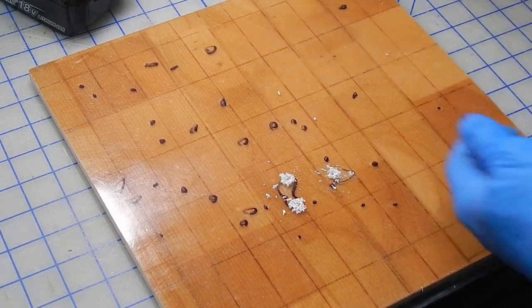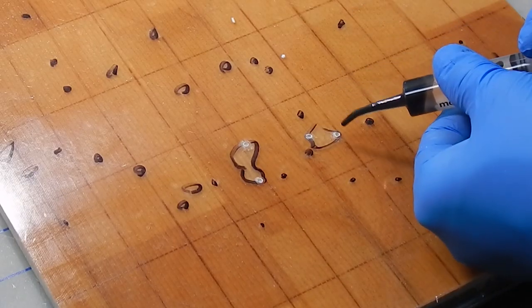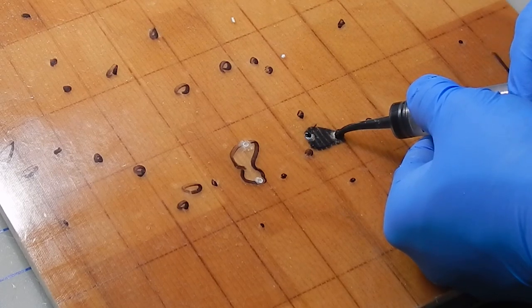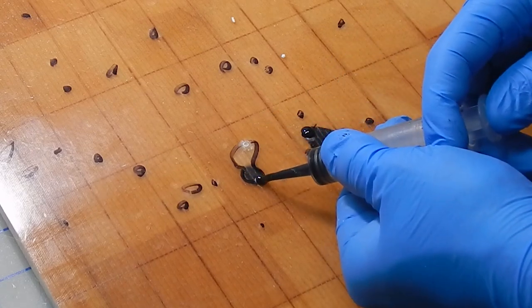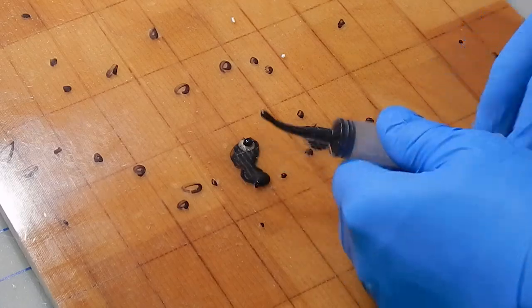So here I am drilling the holes again. And in this case there are no cells of honeycomb to suck up the resin. So you can really see how this works. The resin just fills the whole void and comes up through the bleed hole. And so that's a pretty solid way to do that. And it's cool to watch it go when it's colored black like this.